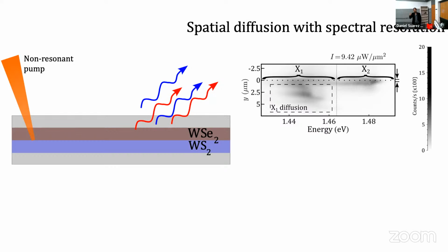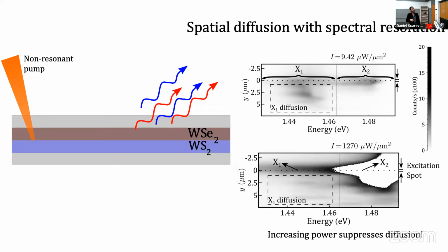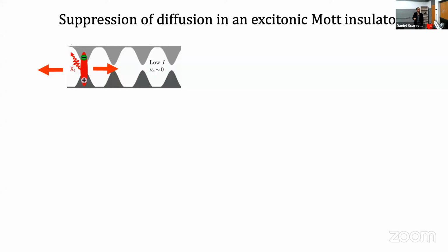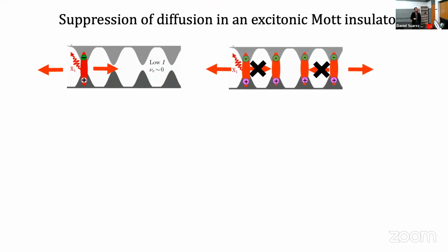But notice what happens when we increase the intensity of the optical pump. You can see the diffusion suppressed. So all we did from here to here was increase the intensity of the optical pump, and by doing that, we suppressed the diffusion of the X1 excitons. This can be understood as follows: if an exciton is in a free lattice, it can diffuse freely. But as we start populating that lattice with other excitons, because of the U terms, or the short-range interaction, they will lock each other in a Mott-insulating state, and then the diffusion is going to be suppressed. And that's precisely what we are observing here.